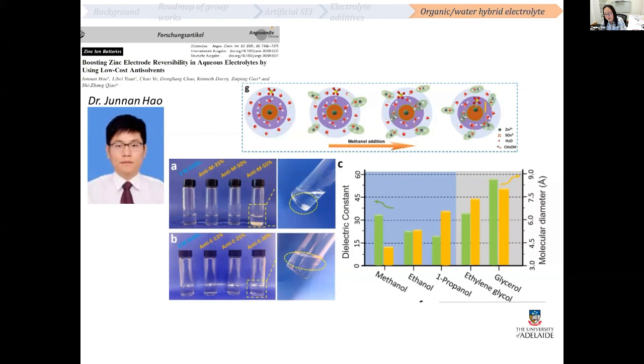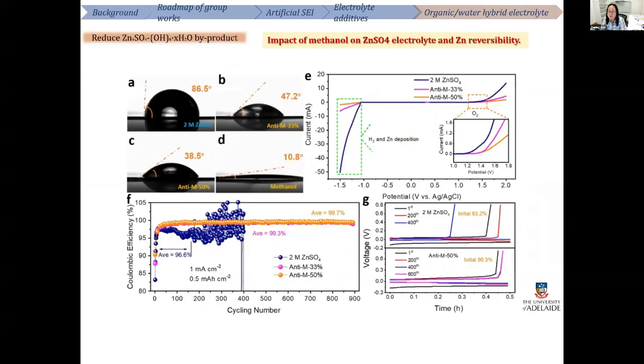And we found that when we increase the methanol ratio to about 50%, we can see crystals at the bottom of this bottle, indicating zinc and sulfate recombine and recrystallize. So therefore, we keep 50% methanol and water as the solvent components for our electrolyte.